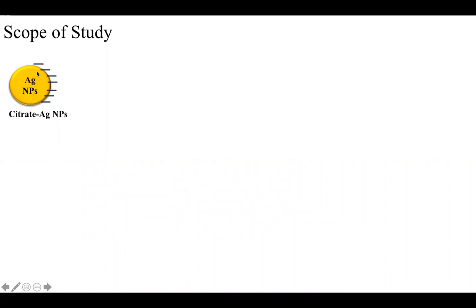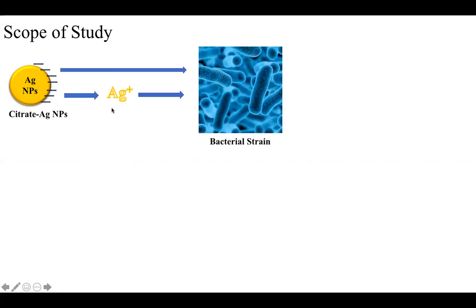We looked at citrate-coated silver nanoparticles with a negative charge on the surface that can interact with bacterial strains in two primarily known routes. One, from the direct uptake of silver nanoparticles to the surface of bacterial strains, or two, the release of silver ions, Ag+, that can be taken up or cause damage to the bacterial cells. But these are studies that have been done, looking at them independently.